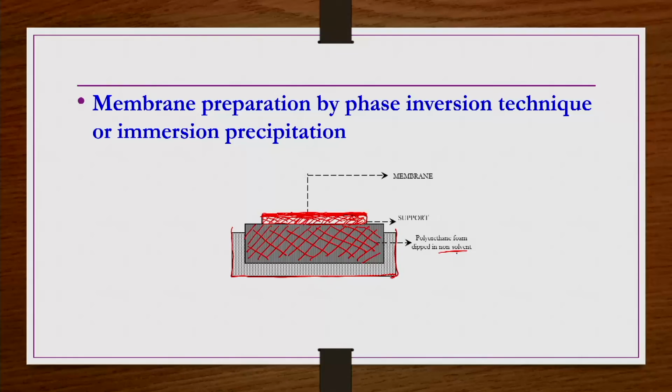So why is this non-solvent required here? If you do not take the non-solvent and do not allow the porous structure of the clay support to be filled or occupied by the non-solvent, whatever polymer solution is there will go inside the porous structure of the macroporous support and block the pores, rather than giving a membrane with a proper porous structure.